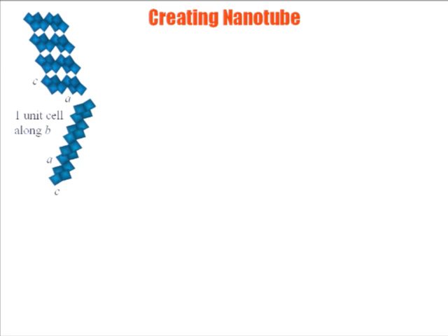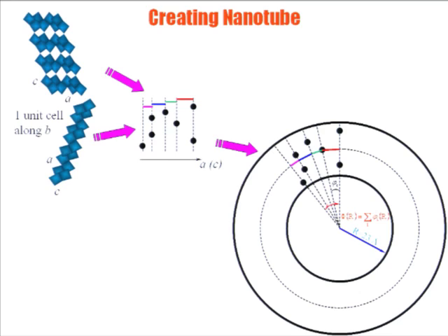After that, it was the matter of creating this type of segments and filling up the tubes. Basically you place all atoms on some kind of imaginary lines perpendicular either to the a axis for this case or perpendicular to the c axis, like in this case, and then create the nanotube geometrically and take these lines and place them in the radial direction.